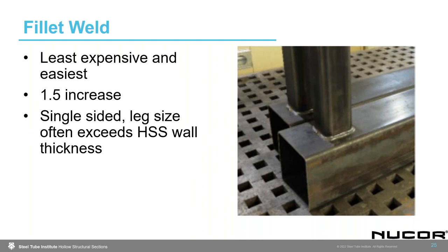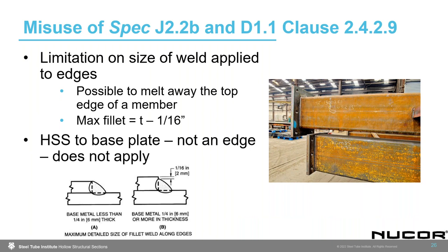Starting first with fillet welds. We love them. It's well known that these are the least expensive and the easiest welds to make. There are considerations for a 1.5 increase that we need to talk about coming up here. But again, as I mentioned earlier, I want to reiterate here, the biggest difference between HSS connections and those connections to open members like wide flanges, channels, angles, is that they have to be single-sided. We don't have access to both sides of a tube wall typically. And so the leg size can often exceed the HSS wall thickness.